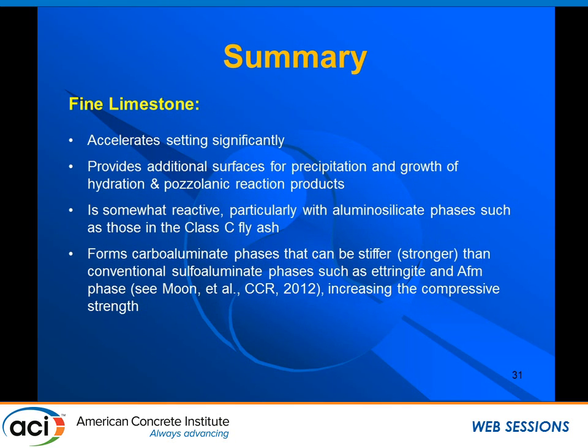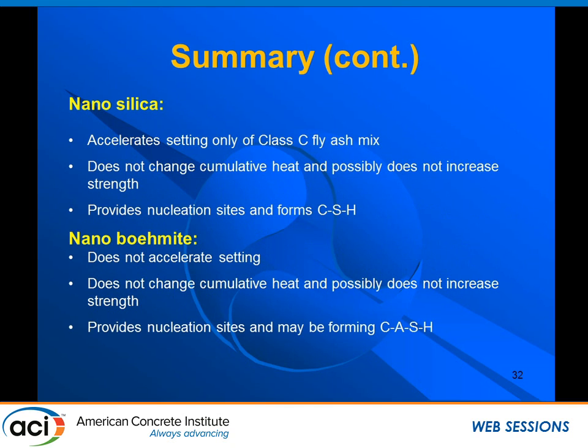Summary: fine limestone, as everybody knows already, helps accelerate the reactions and helps with the strength. Nano silica did accelerate setting, but only for the fly ash. It did not change the cumulative heat, so we don't expect it to help with the strength, but it provides nucleation sites for CSH. For the nano boehmite, it did not accelerate setting.